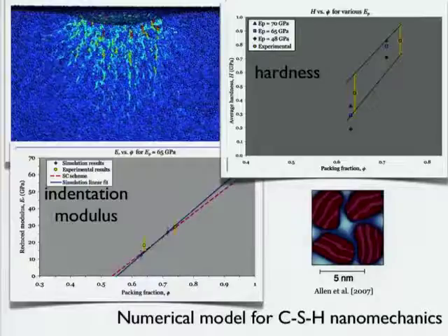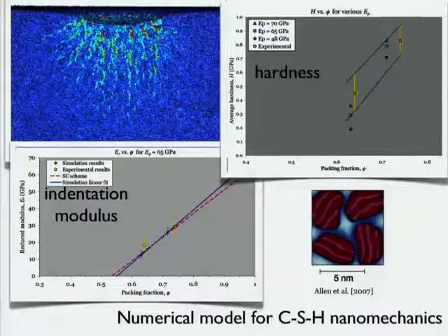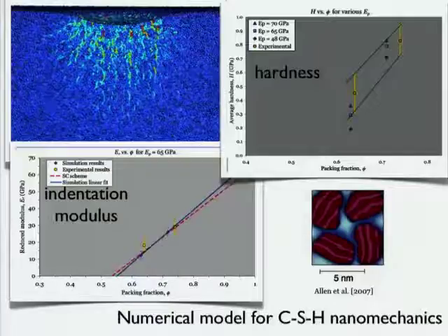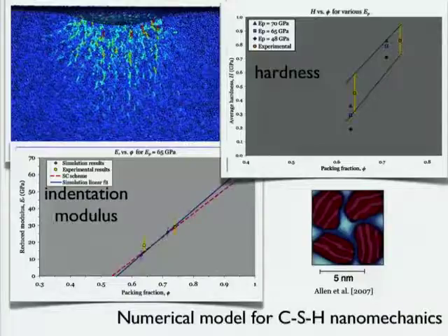And in nanoindentation, you measure a couple of parameters, hardness and indentation modulus. And we're testing two kinds of cements here, one at lower packing fraction and one at higher packing fraction. So you can see here that the yellow results show certain spread in the test data. And then we come with our supercomputer model, and we make a prediction of what the hardness would be and what the indentation modulus would be for those same packing ratios for this cement. And these are our predictions in blue here from the mathematical supercomputer model. Without fine-tuning, without calibrating the model to give you what it wants, to make a true prediction. And you can see that the data is not too far away from, let's say, quote-unquote reality, if you can believe results from MIT, that is.